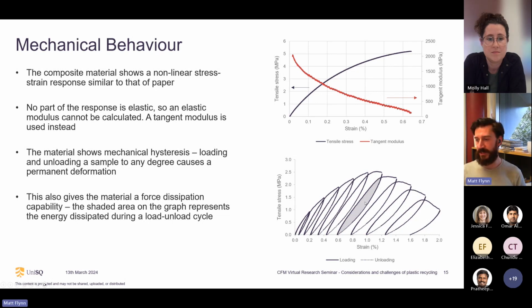But one thing that we see from this is this area between the loading and unloading curves is actually sort of a force dissipation. So it absorbs some of the energy which gets dissipated as heat ultimately. So there might be some applications in damping and impact absorbing and that kind of thing in this material. And this is a similar response to what we see in paper. So the paper that's making up the bulk of the material is imparting some of its mechanical properties, even though the bonding is all done through the plastic.